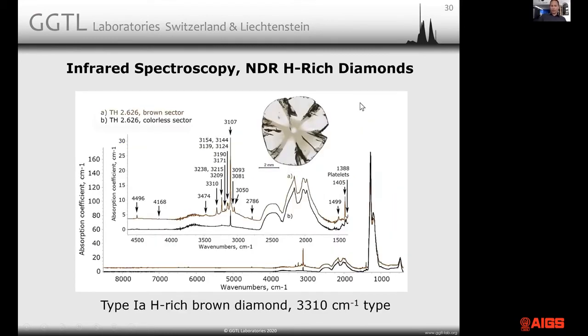Compared to this, the other H-rich diamond, which we call the 3310 centimeter minus 1 type, because that's what distinguishes them. The normal H-rich stone we've seen before has a relatively simple hydrogen spectrum with mostly 3107 plus 3238 and all combinations and overtones. This stone in the brown sectors shows a much more complex spectrum that's related straight to cuboid growth. So in cuboid growth, you find this type of hydrogen infrared absorptions. And just to show that this is factual, I took spectra of the colorless sectors and spectra of the brown sectors.